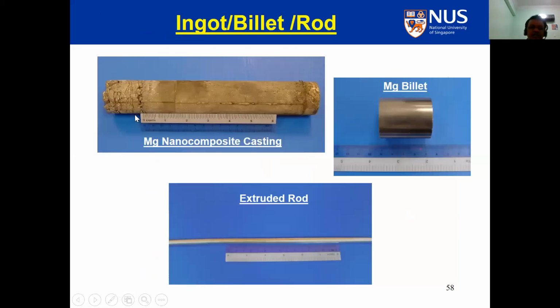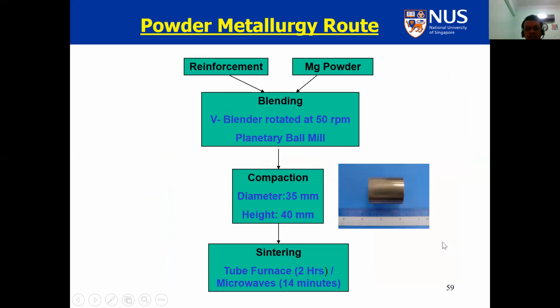You can get an ingot the way the industry wants to have it. You can push it into billet. You can also extrude it. For the powder metallurgy route, normally people mix the magnesium powder with the reinforcement. They blend it. They use either a V-blender or the planetary ball mill. They compact it, and then you can sinter it.